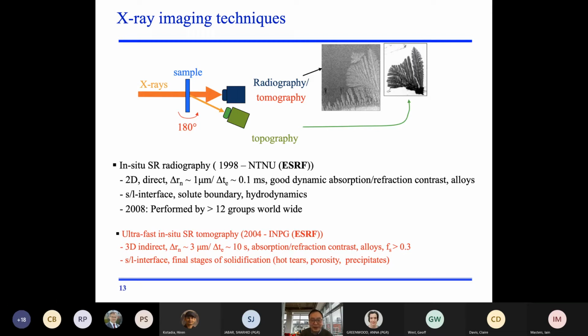There are probably many groups now in the world using this method to look into it. And nowadays, you can also look into ultra-fast methods, and essentially you will get much finer kinetics because you can do a faster sampling rate, and you can look into hot tearing, porosity formation, even precipitates can be studied using this ultra-fast synchrotron X-ray tomography.